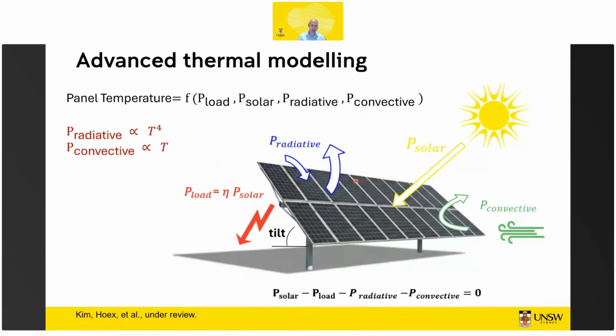There's very strong temperature dependence for UVID. It was a little bit in the results presented by Peter Hacke, but we'll definitely be talking more about that in the future. And then if we look at the heat equation for a module, it's quite complicated. There's of course the solar radiation, then you have radiative cooling, so radiative interaction with the surroundings, then you have convective, so wind cooling. But then also what's often ignored is that electricity is also a way to take out energy, and so the operating conditions of your module affect the temperature.